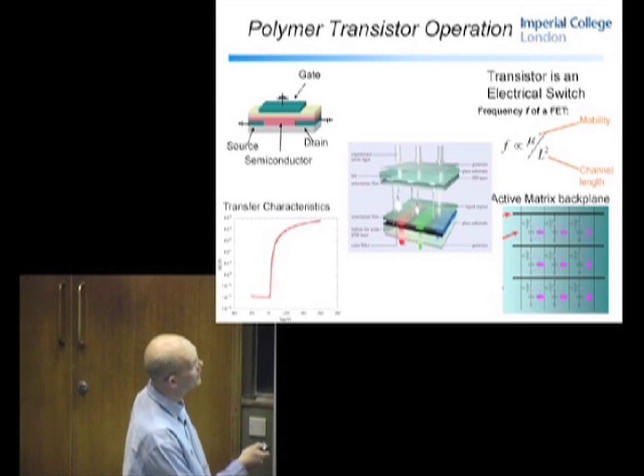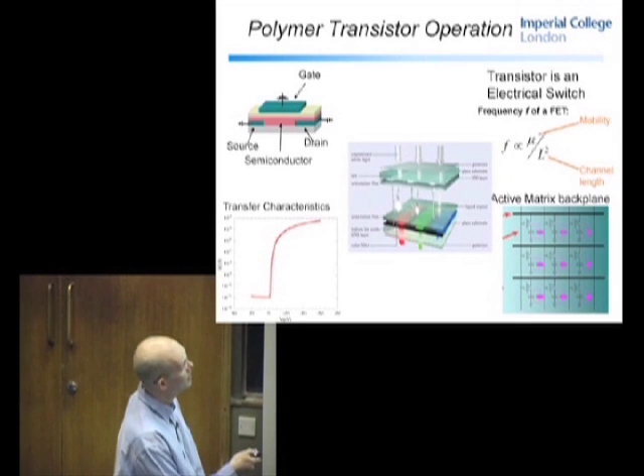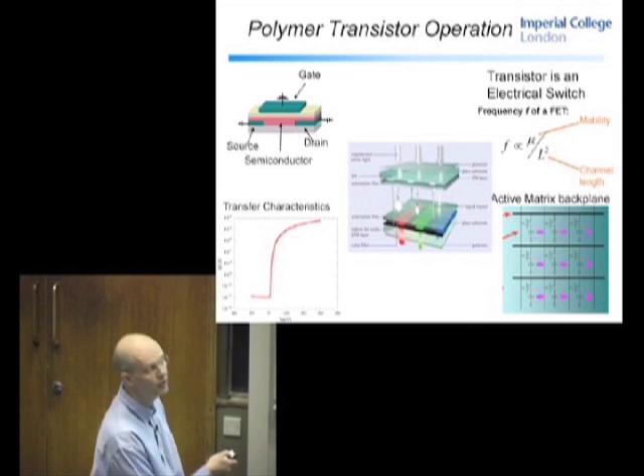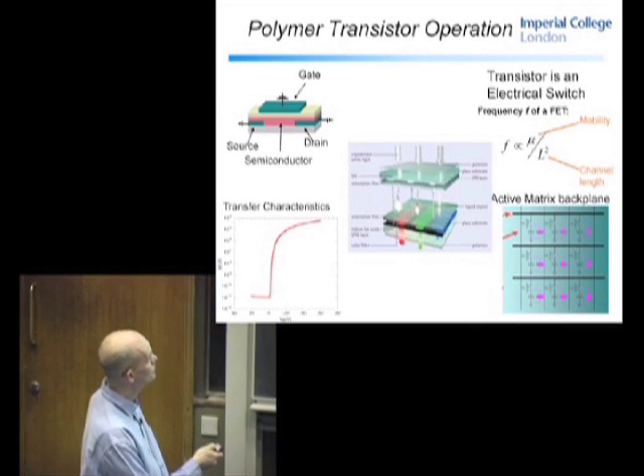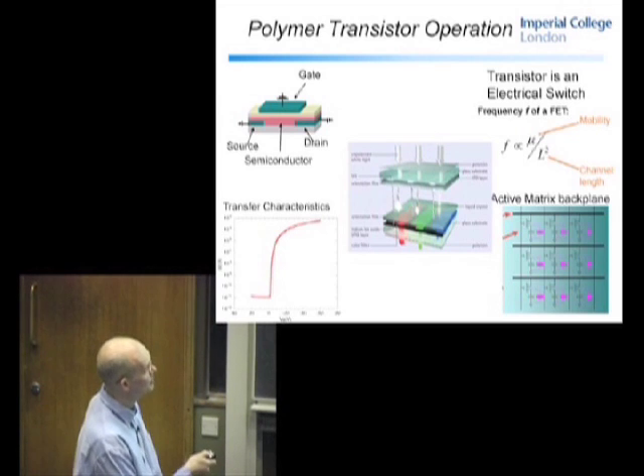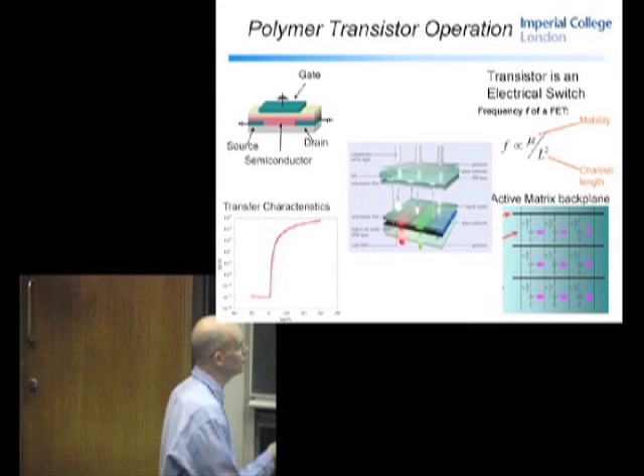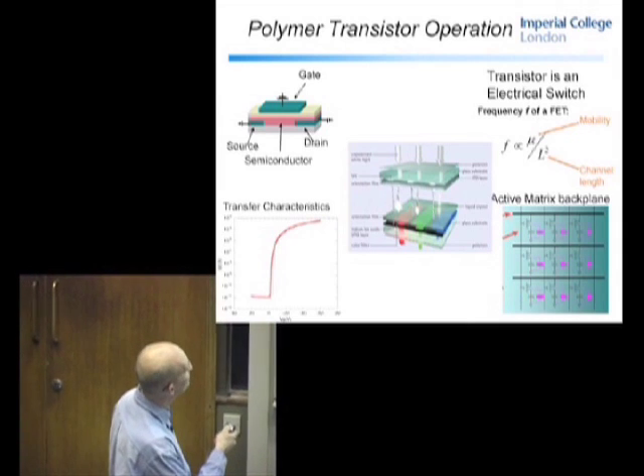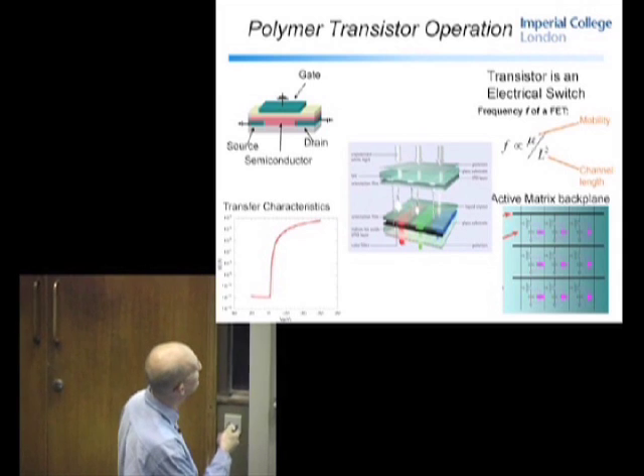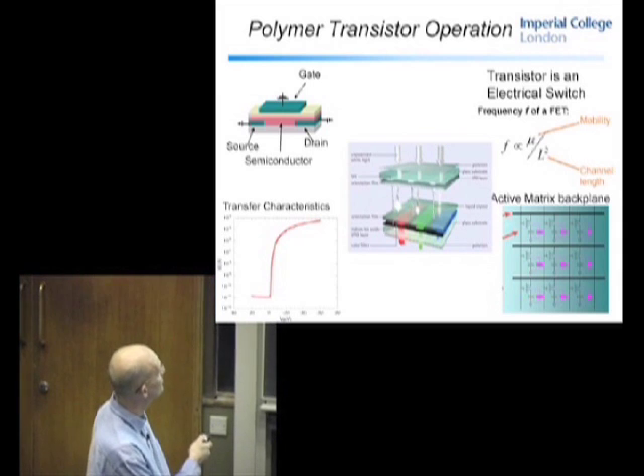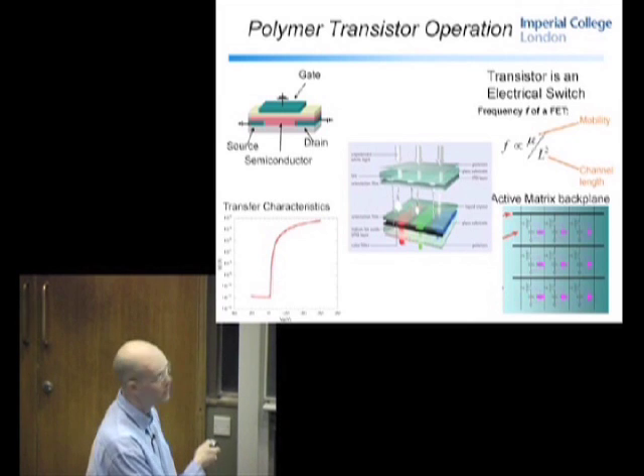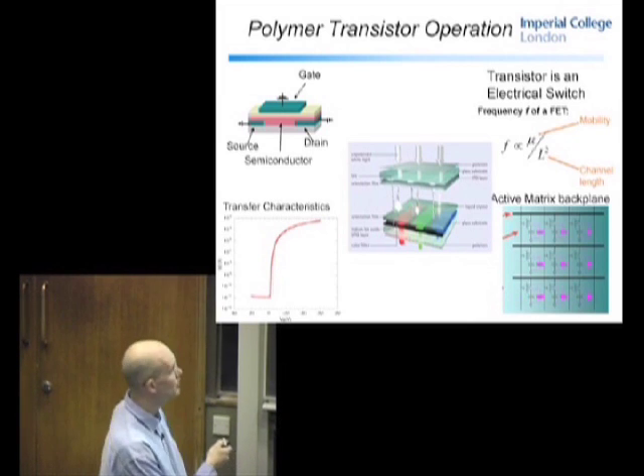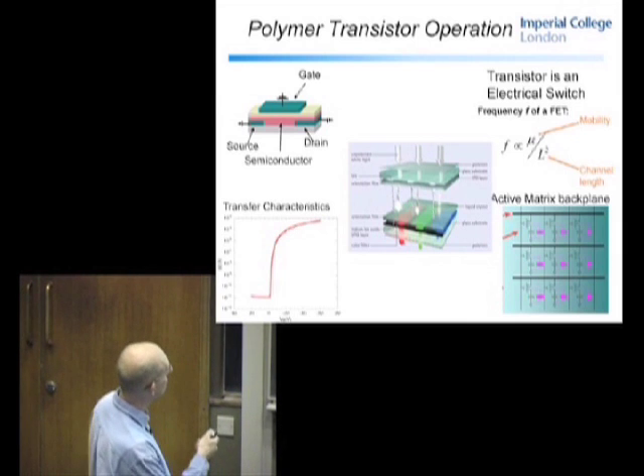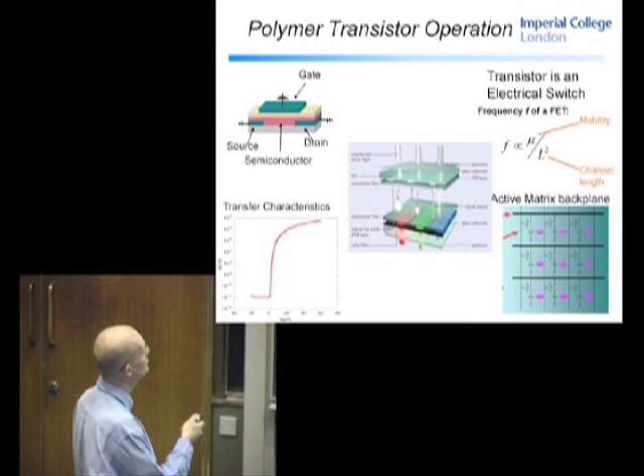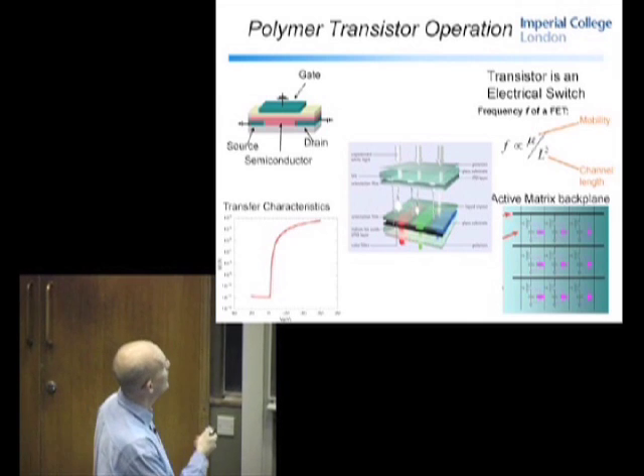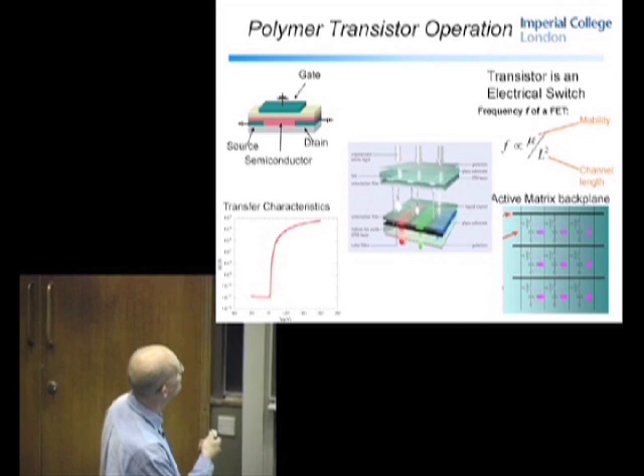And just skipping to here, why that's important is that the frequency of the device is proportional to the inverse square of the channel length. So the longer the channel length with the same mobility, the lower the frequency of operation. So on top of the semiconductor you have an insulator dielectric layer. This, I should mention, isn't drawn to scale. Typically the semiconductor is maybe about 100 nanometers thick, and the dielectric might be 1 micron or so thick, so this is a much thicker layer. And then you have a gate electrode which basically switches on and off the device.